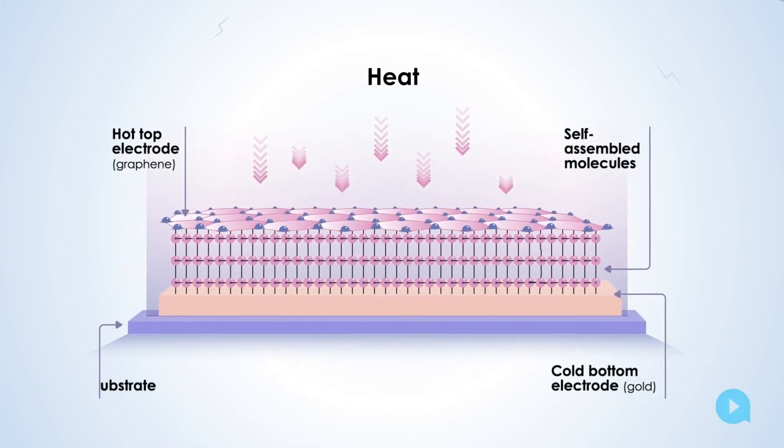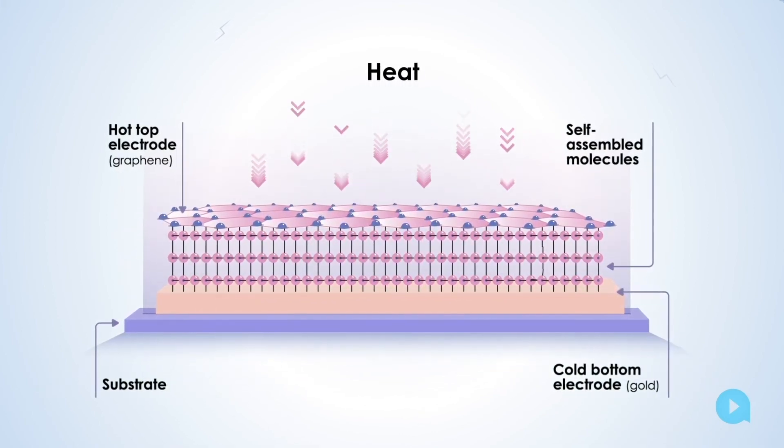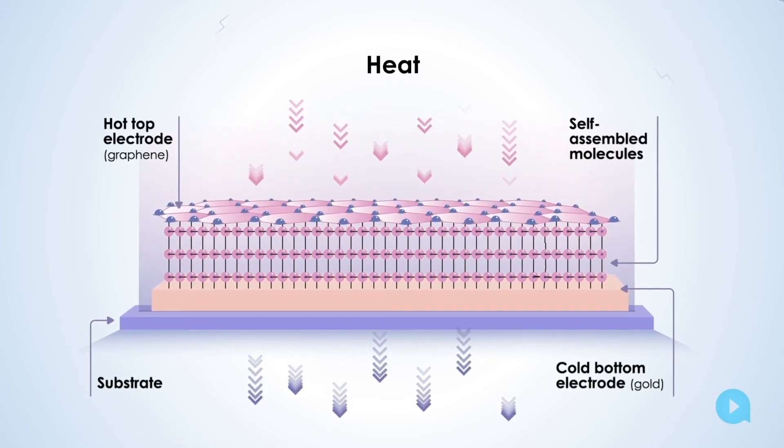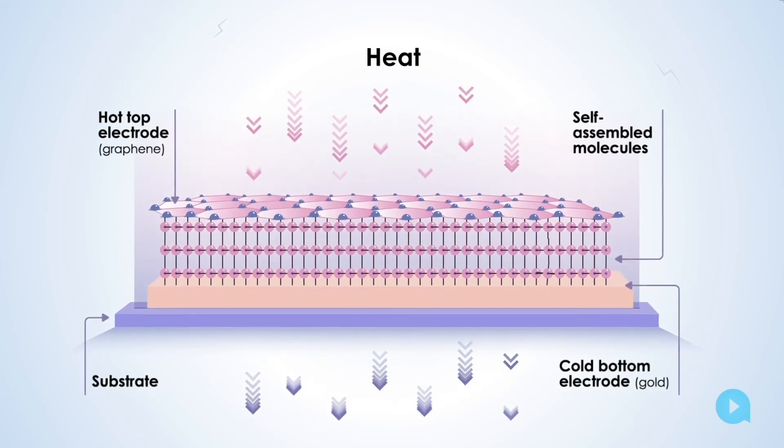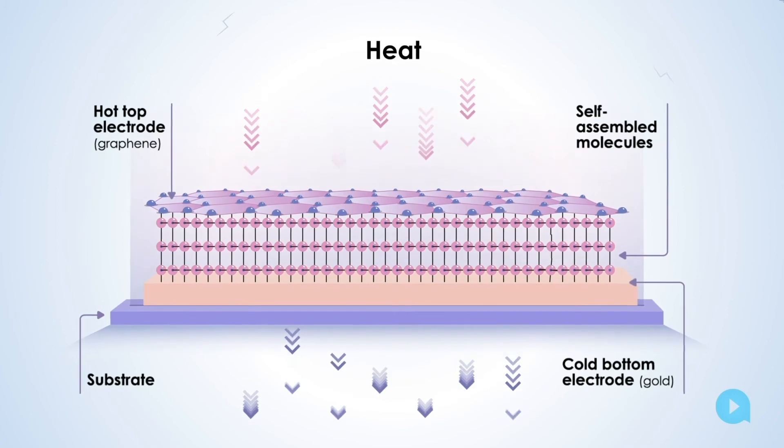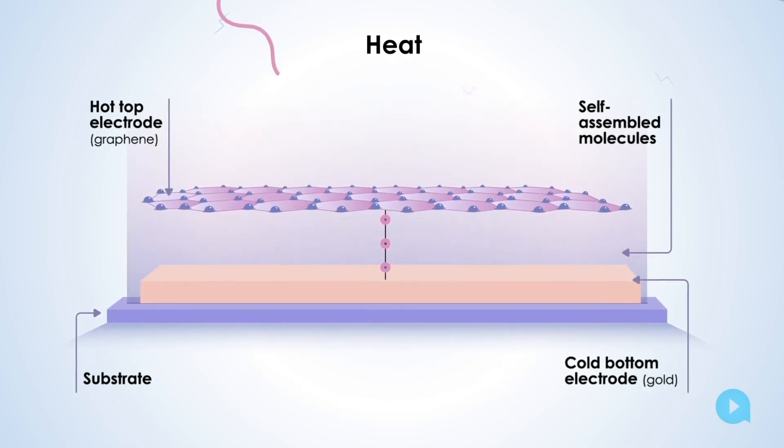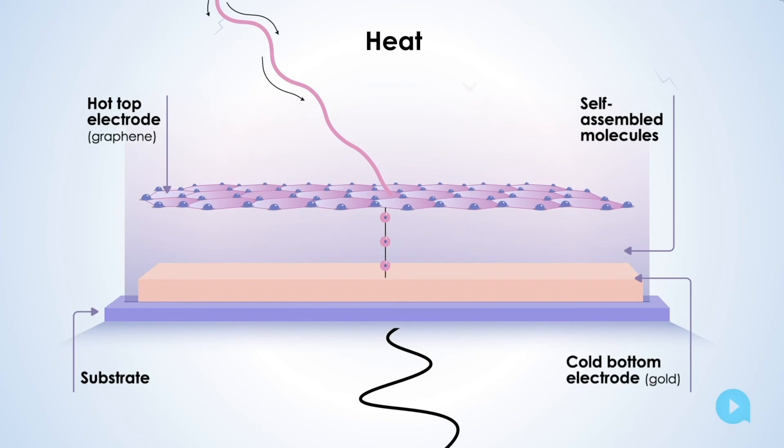That's great, but there's a catch. If the molecules conduct heat as well as they conduct electricity, then we're in trouble. The hot side will start to cool down because its atoms are vibrating a lot and can send a wave of vibration carrying heat energy along the molecule to the cold side.